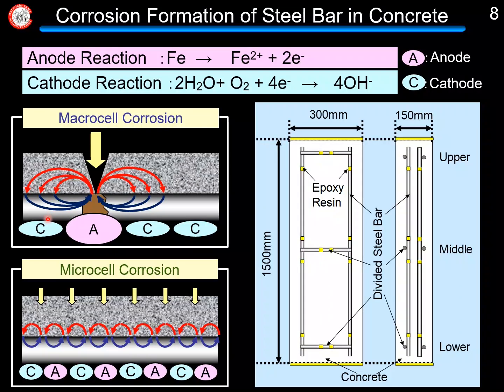On the other hand, the anode and cathode are uniformly distributed in the case of microcell corrosion. In the present study, in order to separately evaluate these corrosion formations, divided steel bars are used. Here, the divided steel bar consists of some small steel elements, and the neighboring steel elements are connected by non-electrically conductive epoxy resin, and these elements are electrically hooked up by lead wire. Using this divided steel bar, we can obtain macrocell and microcell corrosion rates separately.